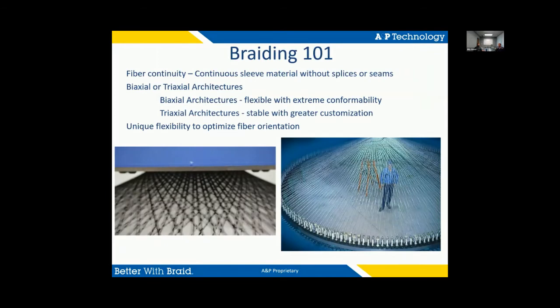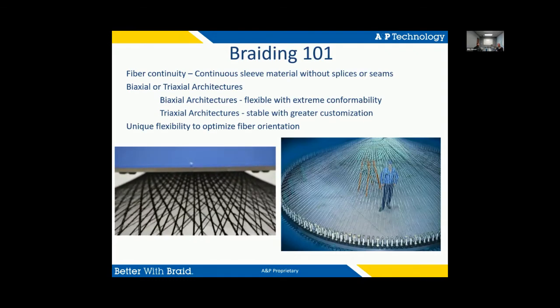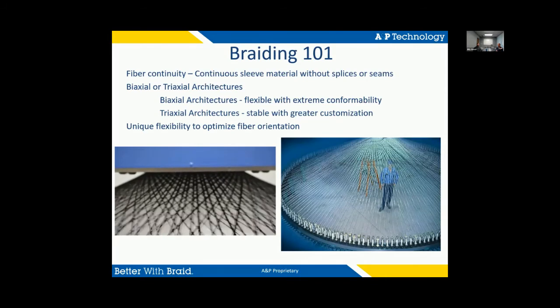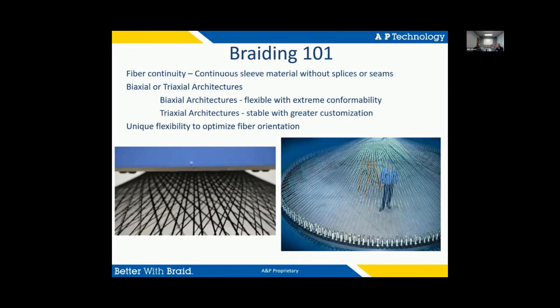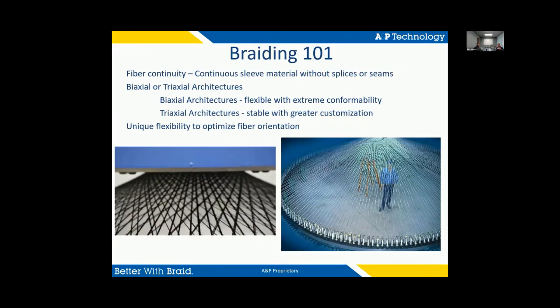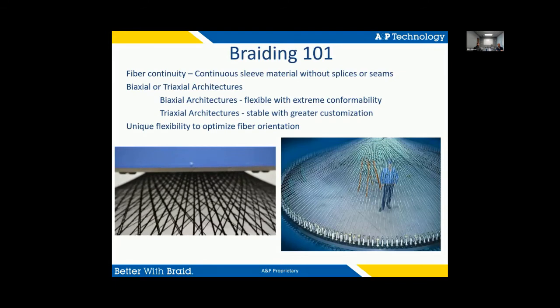So what is braiding? Just at a high level, it's going to create fiber continuity in the form of a sock or a sleeving at a 2x2 twill architecture. Nominally, we'd like to orient everything at plus or minus 45, but the real advantage to braid is that we can orient those angles and work with the customer to optimize performance anywhere from plus or minus 15 all the way up to about plus or minus 80. Braid has the ability to be both biaxial, again, that plus or minus 15 to plus or minus 80, or triaxial, so incorporating a 0-degree yarn or axis of orientation as well.